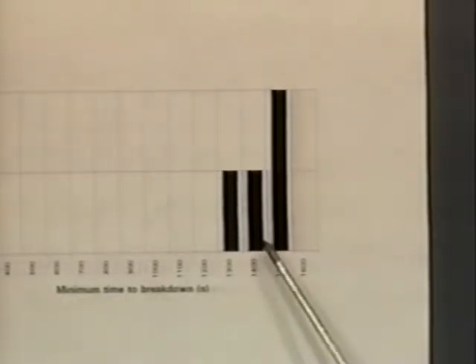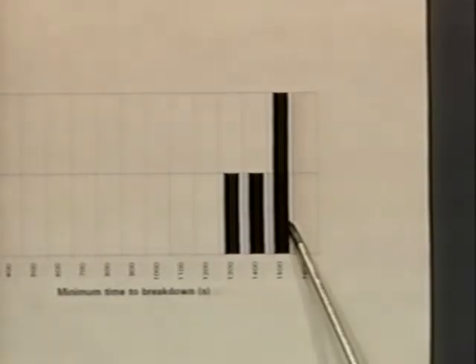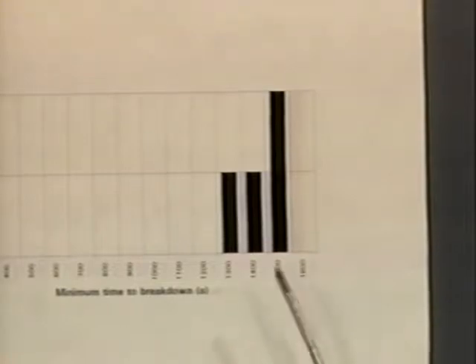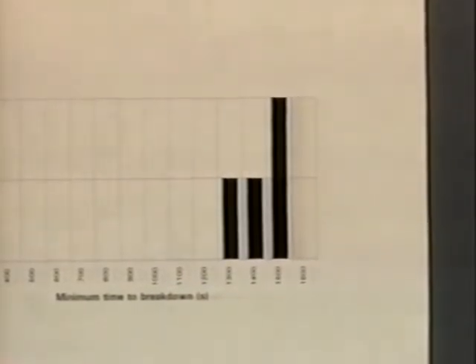small area devices. And I can't wait to get back and harass my students for more data, particularly voltage and thickness dependent. Because if other thicknesses last 1,500 seconds as well, then finally we see that breakdown and positive charge are related to each other, that we really are looking at a fundamental effect, a degradation effect in the oxides. And if that's the case, then I'm really excited, and my hypothesis, this interpretation of QBD is correct, that breakdown above the thresholds is just a time evolution effect.